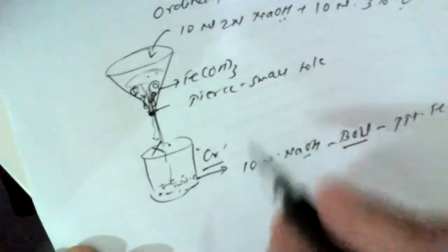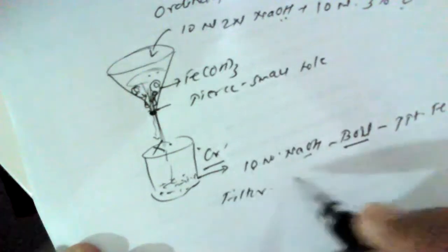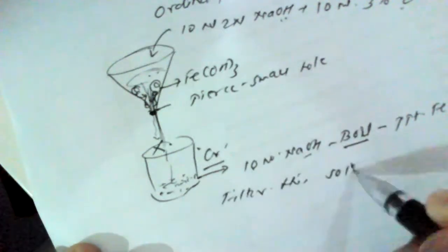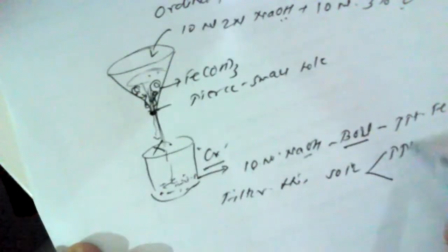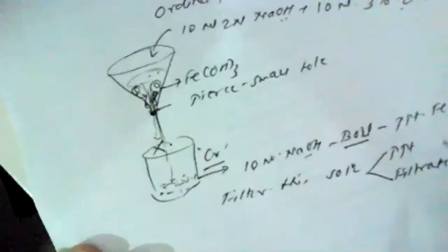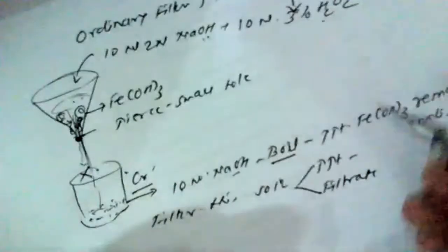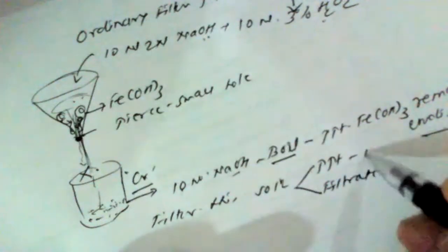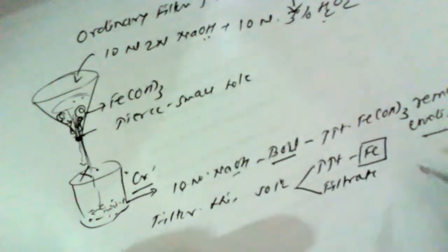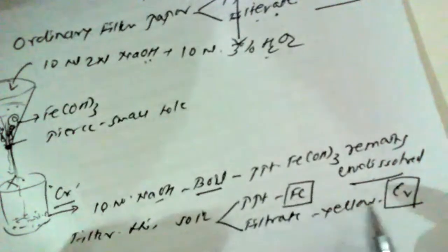For this purpose, we have to filter this solution. After filtration, again we have obtained a precipitate and a filtrate. The precipitate which remains undissolved, collected on a filter paper, is ferric hydroxide, and the filtrate, which is yellow in color, is definitely of chromium. So this is how we have separated iron from chromium. Now the things are very simple. We have to estimate iron first, followed by chromium.